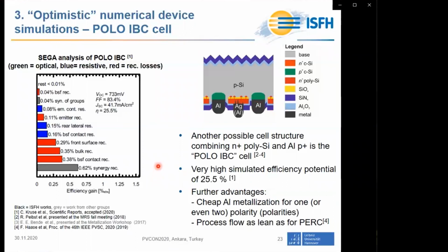The synergistic efficiency gain analysis is shown here in the left-hand graph, and you can see that the optical losses due to finger shading have disappeared, of course, because it's an IBC cell, and the most relevant loss channels are recombination induced. There is a gray bar here, and this corresponds to the synergy of all recombination loss channels. That means, due to the liquid bucket principle, you could achieve an even higher efficiency than the sum of all recombination losses if you succeed in suppressing all recombination losses at once. Again, the same advantages apply here as for the POLO back junction cell, although the cell processing is a bit more complicated than for the POLO back junction cell. Nevertheless, it is still as lean as for the PERC cell.